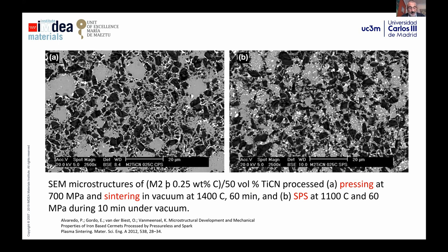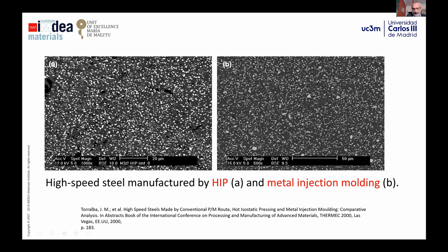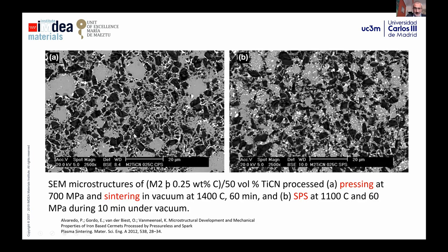This is produced by Pablo Alvaredo and other authors, in which you see on the left one material, a composite, an iron-based composite with titanium carbonitrides, just for cutting applications. You can get this microstructure on the left by press and sintering, but you have to reach 700 megapascal in pressing and 1400 degrees with a dwell time of 60 min to reach this microstructure.